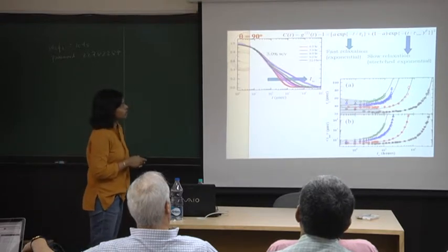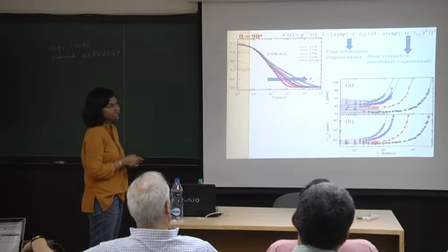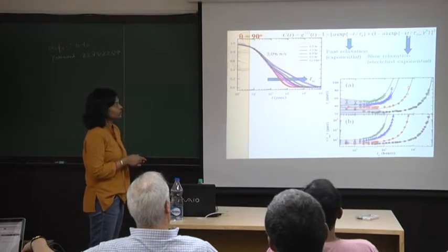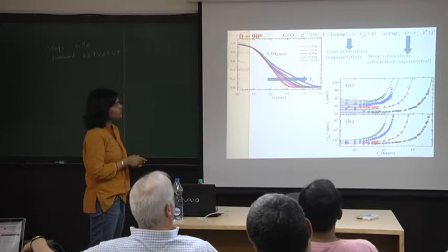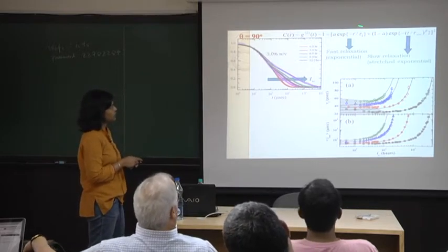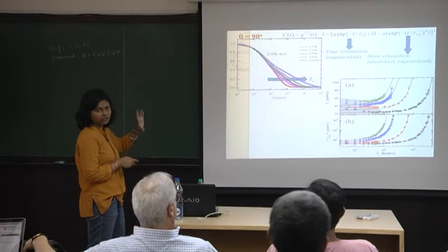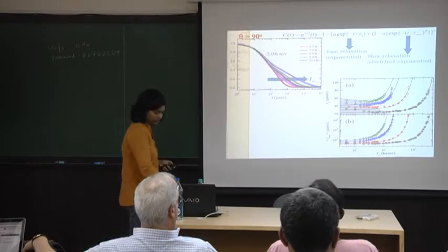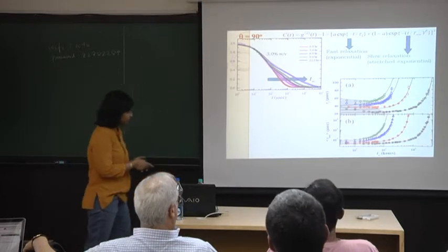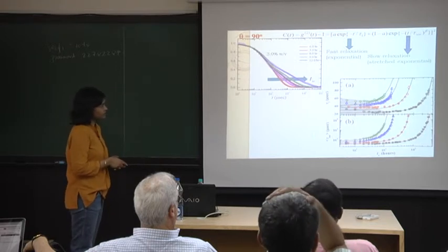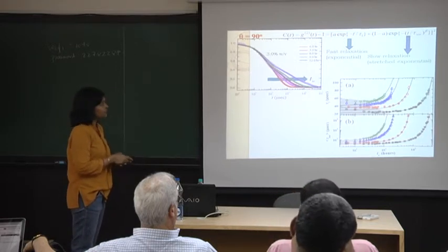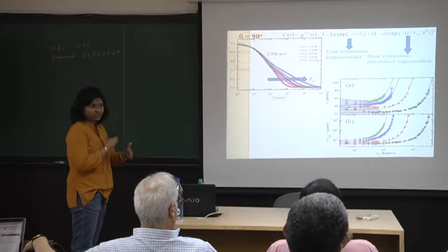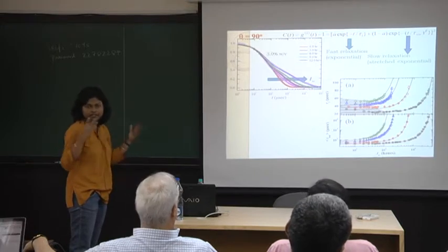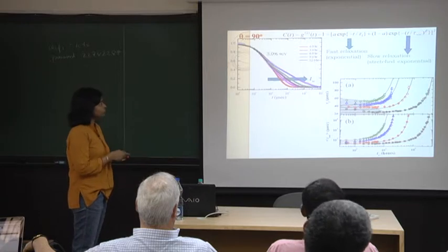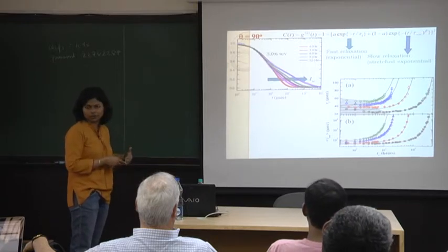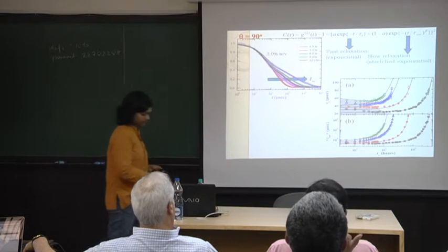So here are our fitting parameters. This is the fast relaxation time scale tau 1. This is the slow relaxation time scale tau WW. Beta is the stretching exponent, and there's a piece A which tells you the relative fraction of the two relaxation processes. So what I've plotted here versus the age of the sample is the fast and the slow relaxation times, and you can see that they both evolve. As you're just letting your sample spontaneously do its own thing, both these time scales, the fast as well as the slow, evolve.